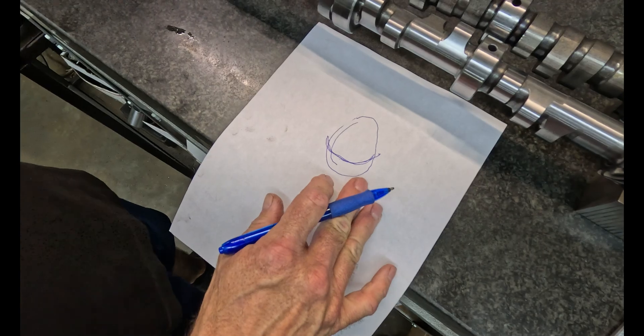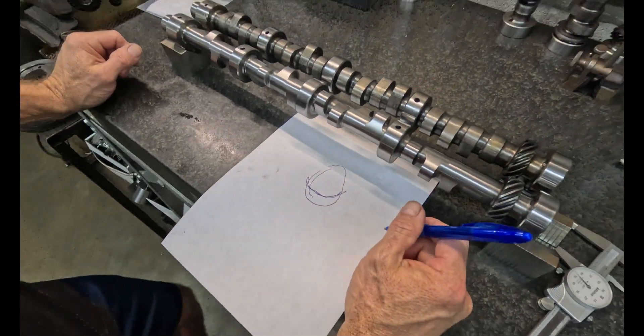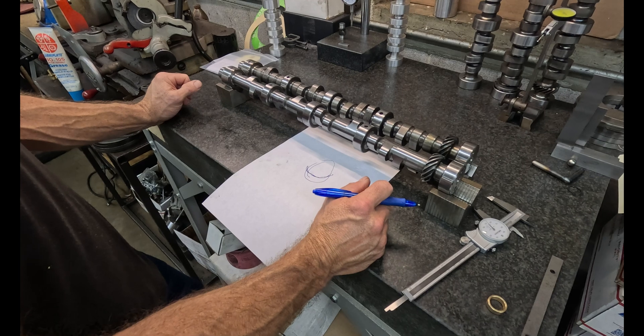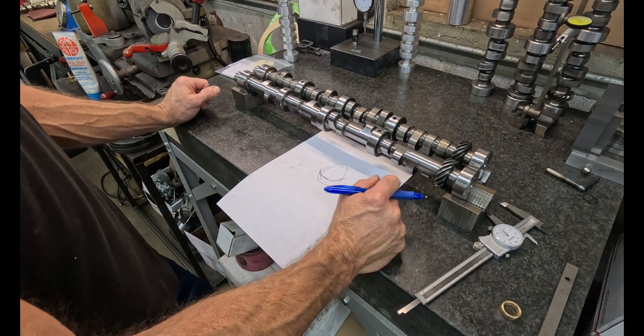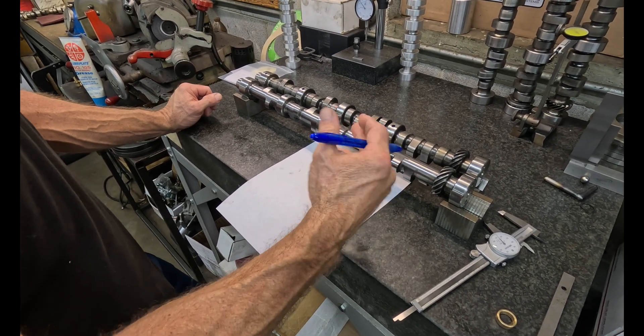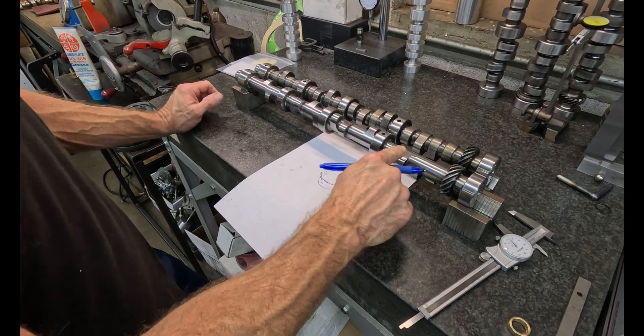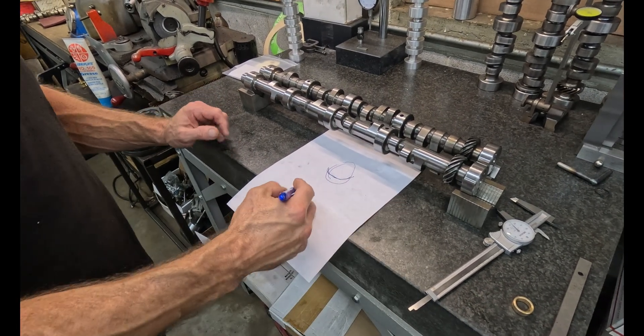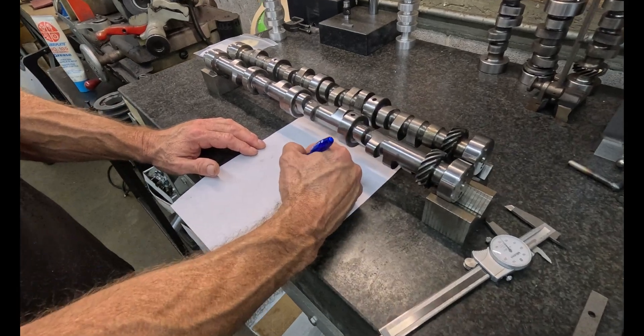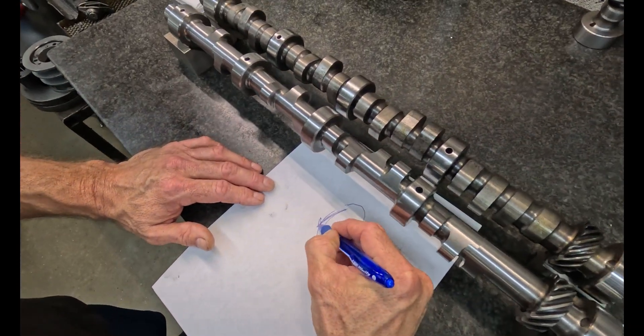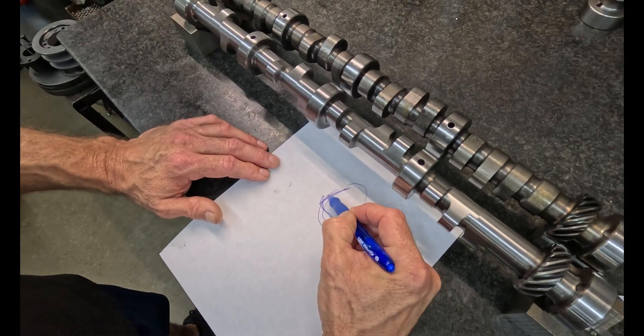And so we'll go over to the Rockwell tester, but I tested it, and it should be pretty close to 60 Rockwell. And on the base circle side, this core is 30, which is the base material. I mean, the base material would be 25 to 30 Rockwell. So, and then as it comes up the side, it just fades out into nothing, the heat treat line.